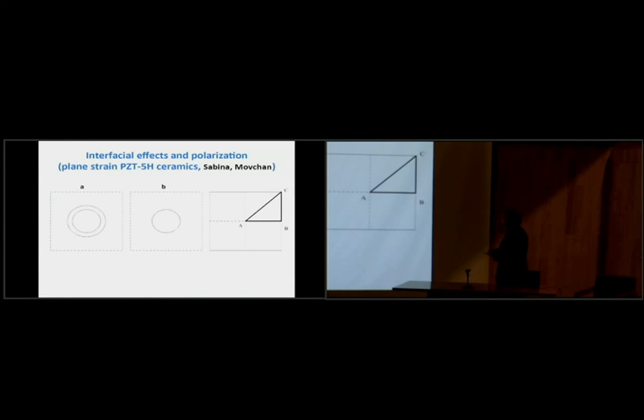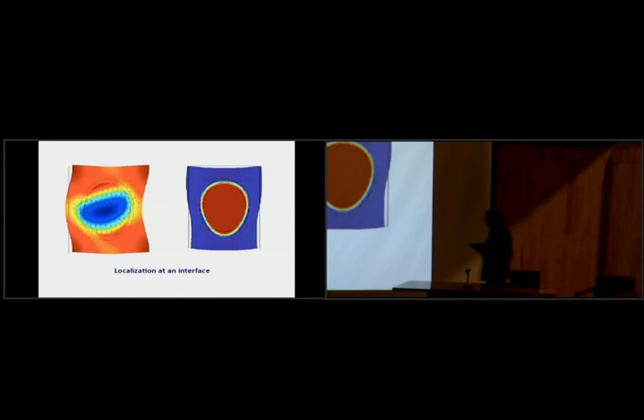So then again, we choose the symmetry of the structure. In this case, the test computation was done for PZT5 ceramics, and that's the problem we looked at a number of years ago together with Professor Sabina. And then you can certainly see interesting dispersion relations and localization near the interface boundaries. So here, the electric potential is shown by color, so that's the surface. Then the actual electric field is shown by arrows, and the deformation is the deformation. So you can clearly see the localization near the interface.